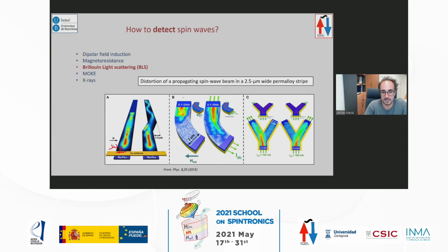Here, the same, they excite it from here, and they see that under certain conditions, spin waves can turn, in a straight line or in a curved line. And here, what they show is that by exciting spin waves in this direction with the electrical current, you can decide whether spin waves go in this direction or in this other direction. So this is about how to modify spin waves, and this is an excellent technique to do these experiments.